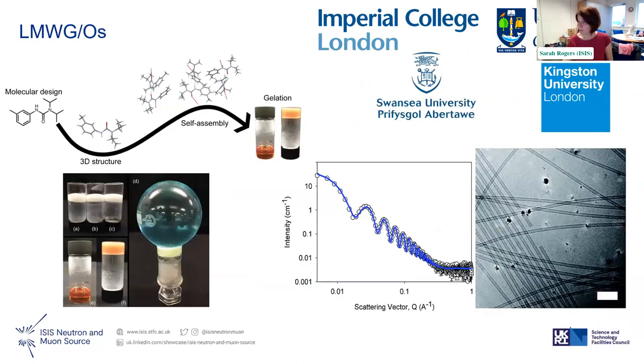So another example I wanted to talk about was these low molecular weight gels or organogels. It's kind of a growing area of interest. And again, this has been work that's been supported by various universities, as you can see there. Generally, they are a molecularly designed molecule that has a 3D structure, it self-assembles and forms a gel. And we can use scattering alongside things like microscopy to really understand the structures and how they change in situ with different triggering conditions.